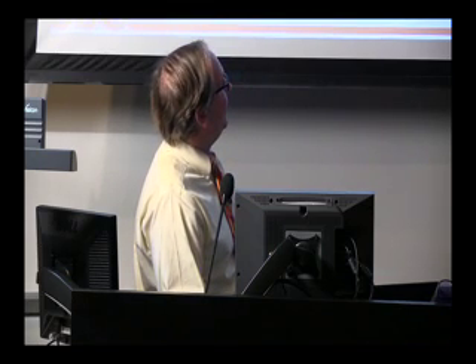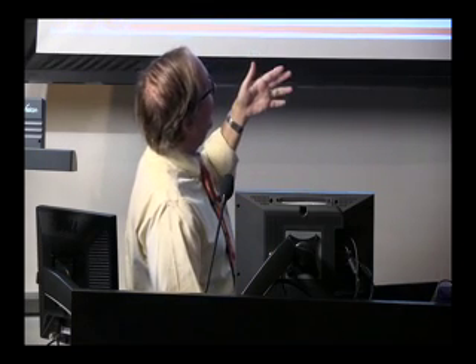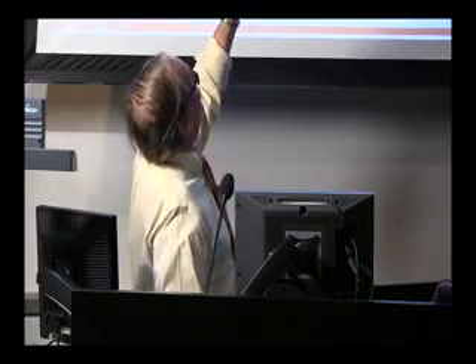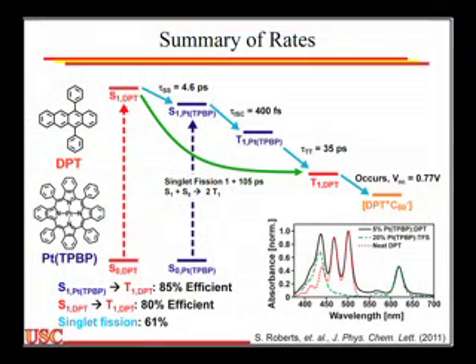So let me just show you my last data slide, and then next to the last data slide. This is just sort of recapping. So we measured these rates. So the singlet transfer is about 4.6 picoseconds, 400 femtoseconds, 35 picoseconds. We've made devices with these, and we get about a 0.77 open circuit voltage, so they actually work. Singlet fission goes at a rate of about 1 plus 105 picoseconds. Remember, this is the bi-exponential one.